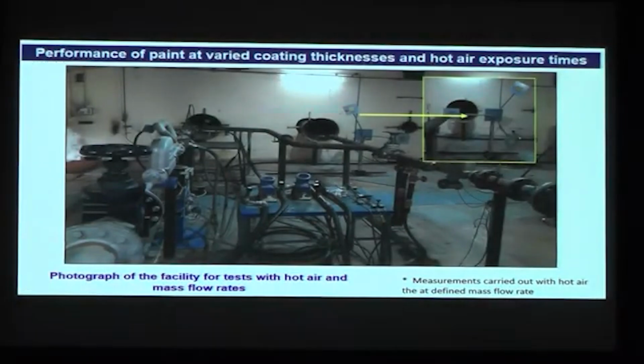This is the photograph of the test rig facility, the gas generator test rig, which was used to evaluate the coating. Now why were the coatings tested at this facility? Because we had to check how effective the coating is in providing thermal insulation against not just the hot air, but it also had to withstand the high mass flow rate. So we generated the hot air with the required mass flow rate in this test rig. You can see the samples mounted on the sample holders over here. Tests were carried out on the coated samples against the uncoated samples. They were carried out on both aircraft grade aluminum alloy and CFRP substrates.